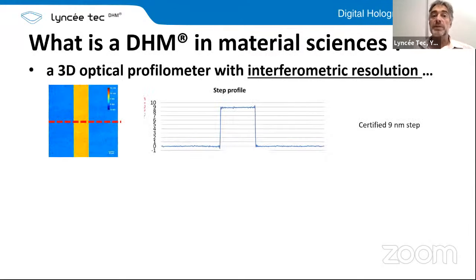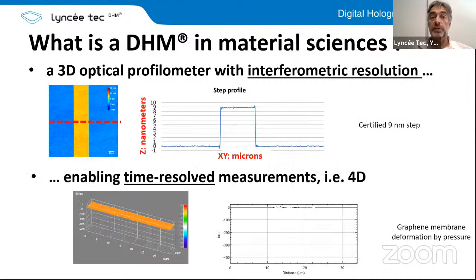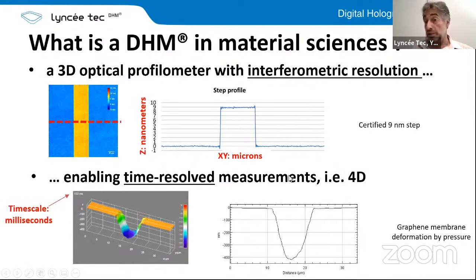So what is a DHM in material science? It's a 3D optical profilometer with a so-called interferometric resolution, which means that vertically we are in the nanometer range, and laterally we are limited by diffraction, so we have typically a micron. Generally, optical profilometers are rather slow because you need to scan either laterally or vertically, or phase scanning, to get your answer. DHM is immediate. So basically you don't need any scanning, so we can make real-time measurements.